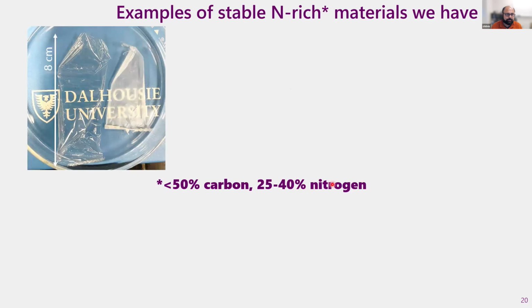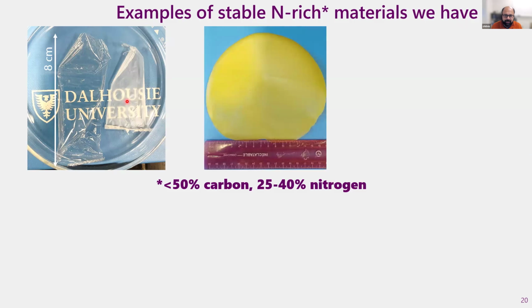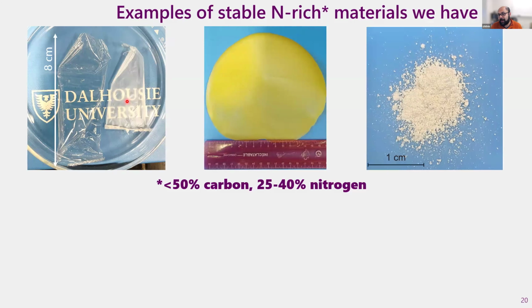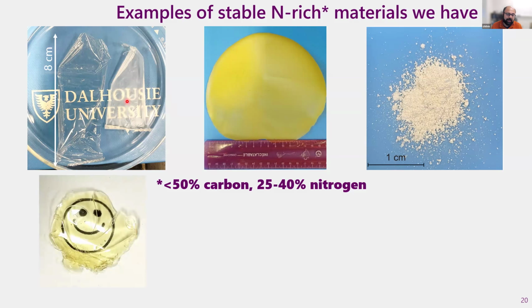So we can make films. This transparent film on the left-hand side looks, feels, stretches, and acts exactly like cling film in your kitchen because you want to make replacements that look, feel, and behave the same without having the negative aspects. So that's intentional. You can make a transparent film or you can make a cloudy film depending upon how you make it. You can make an opaque film. This one looks approximately 15 centimeters, 6 inches long, a circle that was cut out of it, and it's got the consistency of cardboard, right? So it's a thick plastic or cardboard. We can make powders. In many cases, polymers are preferred as powders because then they dissolve faster or they can be pressed more easily and so on. We can make powders as well. We can make rubbery objects. So this is kind of like a gel-like material. We can make objects that have interesting properties.